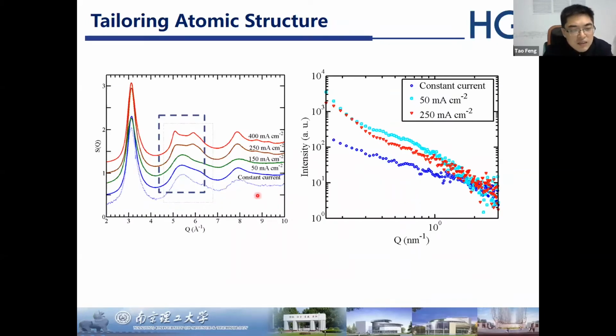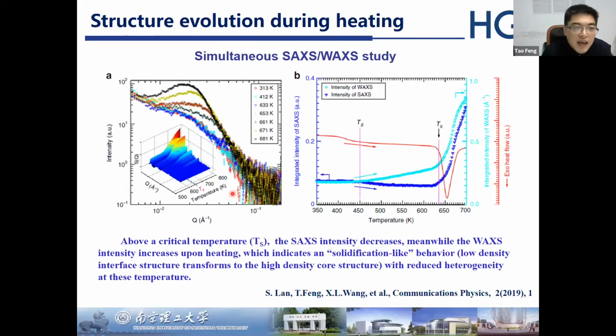And using this electron deposition technique, we can also tailor the atomic structures just by using different deposition rates. And this actually provides more opportunity for us to modify the atomic structure of the metallic glass. And this atomic structure also can be modified by post-heat treatment. Using the synchrotron X-ray diffraction technique, we can perform simultaneous SAXS and WAXS study to investigate the structural evolution upon heating.